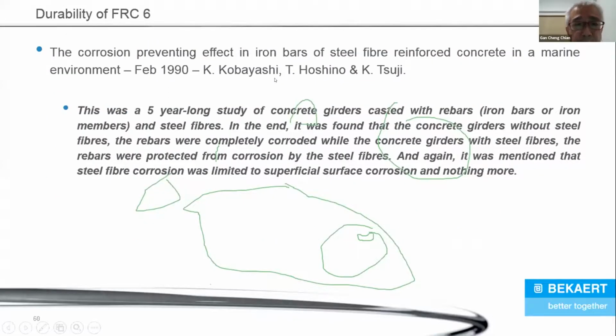And a last paper that came out in 1990 by a Japanese researcher, Dr. Kobayashi. Sadly, Dr. Kobayashi has passed away, but this paper is the only one available that went through a long-term study. They cast a bunch of concrete girders reinforced with rebars and steel fibers. And it was a 5-year-long study. In the end, he found that in the concrete girders without steel fibers, the rebars were completely corroded, while in the concrete girders with steel fibers, the rebars were protected from corrosion by the steel fibers.